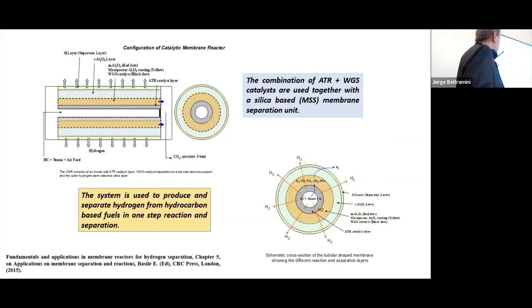We see here that we have a membrane that is an alumina tube. It was alpha alumina, with a coating of gamma alumina, and then we put different coatings of silica. The different coatings of silica give the porosity needed to separate the hydrogen. But in the meantime, into the coating of silica, we put the metal active part of the catalyst. So the catalysis was done in the membrane and the separation was done in the membrane. It was a big challenge because we needed to study diffusion, reaction and then the separation of the hydrogen. That is quite a difficult approach.